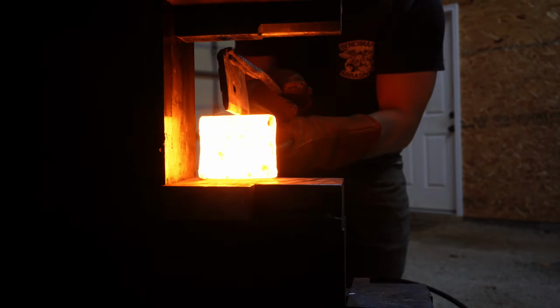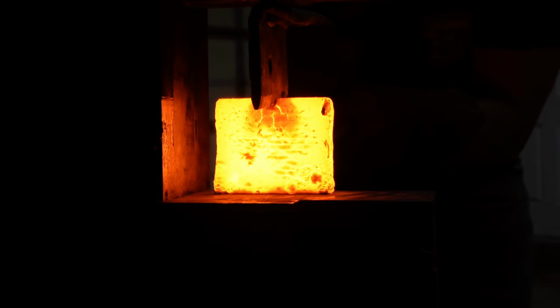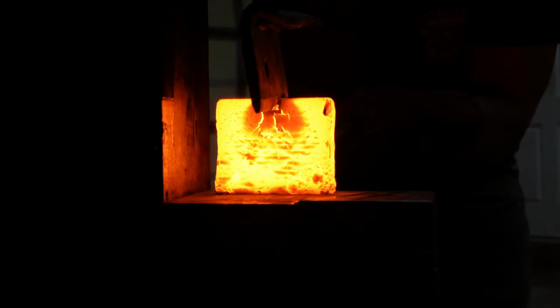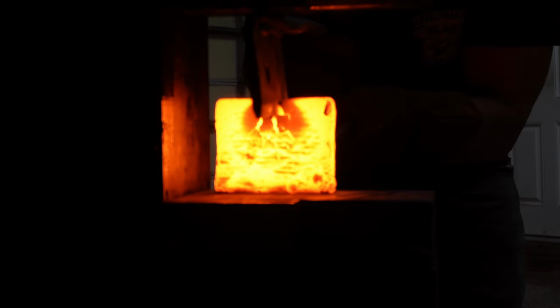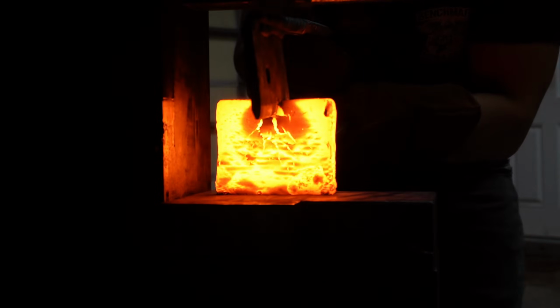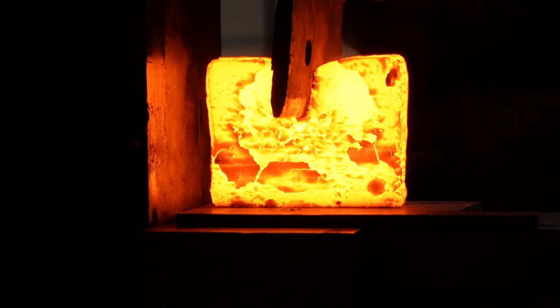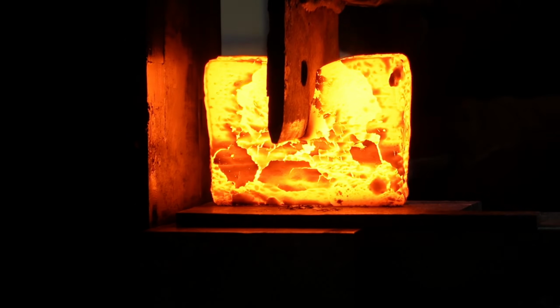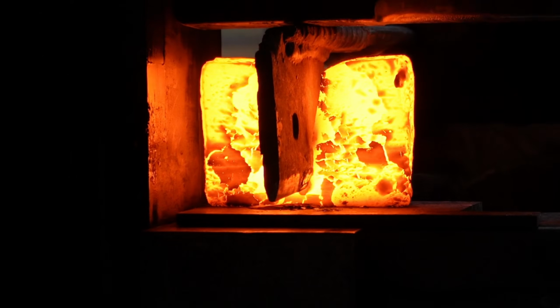The purpose of the splitting process is to use a dull wedge and smash it through the steel while it's at forge welding temperature, basically dragging the layers that it touches downward so that when you forge weld it back together, it creates that beautiful sweeping feather pattern radiating out from that central seam.